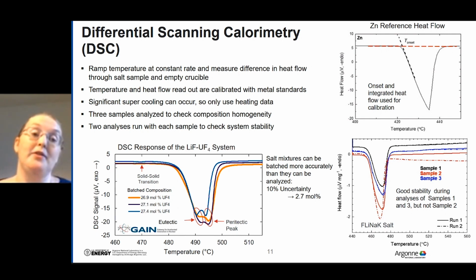And then the figure on the bottom left illustrates further what I was talking about with using batched masses versus measured masses for composition. So you can see that we measured 3 different compositions of this binary under the GAIN voucher, and they span a 0.5 mole % composition range. And you can see that the DSC is certainly sensitive enough to pick up the small differences in the shape and size of the eutectic and peritectic peaks. However, if we were to rely on our measured compositions, the typical uncertainty in the method we use is about 10%. So that equates to 2.7 mole %, which would mean these 3 samples would be indistinguishable from each other. So that's why it's so important to use a higher precision method of indicating your composition, so using the batched compositions.